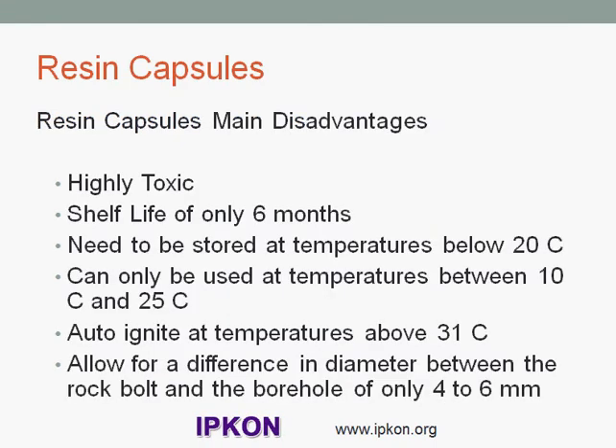So, unless the mine is equipped with a very good ventilation system, after installation of resin capsules, a mine usually has to be evacuated of all its workers for 2 to 3 hours to allow for a proper ventilation and an evacuation of the toxic vapors emanating from the said resin capsules. This can have a significant impact on the productivity of a mine.